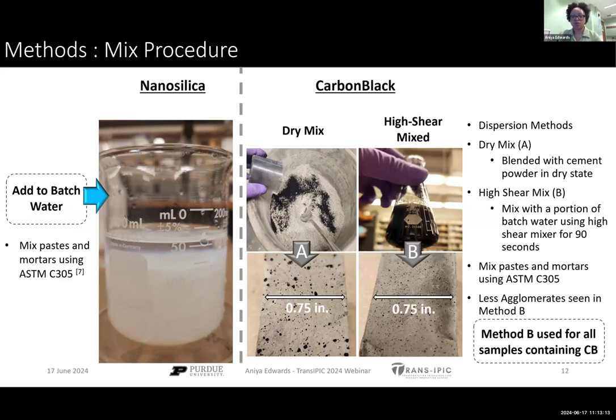The dry mix method simply required the concentration of carbon black being stirred in with the dry cement powder and then mixing. Whereas the high shear mix method required us to add the carbon black to the batch water and then high shear mix it for at least 90 seconds. And what we found was that using method B resulted in fewer agglomerations, as you can see in those bottom 2 photos. And even some of those agglomerations that we might think are carbon black agglomerations are actually pores. So it was much more successful to evenly disperse the carbon black using method B. So we decided to use that method for all future mixes.